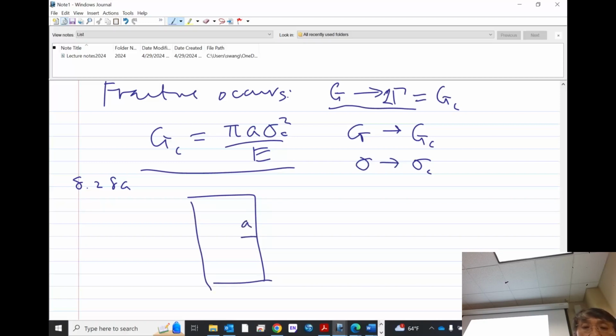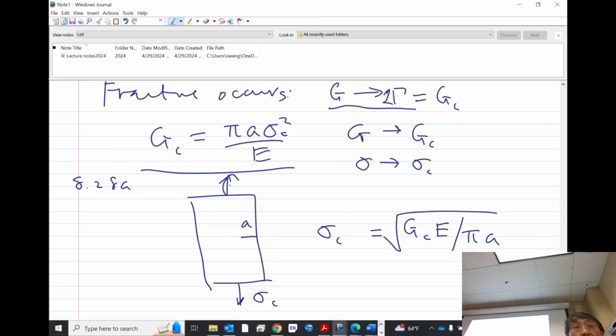With a crack of size A, this result says that the break will occur when sigma C squared is GC Young's modulus divided by pi a. Or moving the square to the other side, I have a square root. This is the celebrated Griffiths scaling law, if you want to call it. I call it Griffiths scaling law.